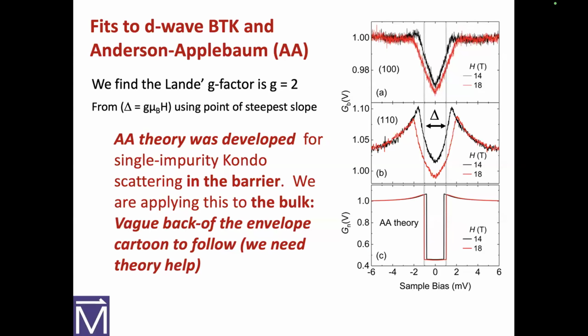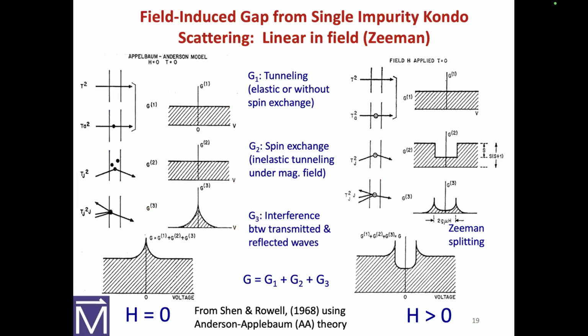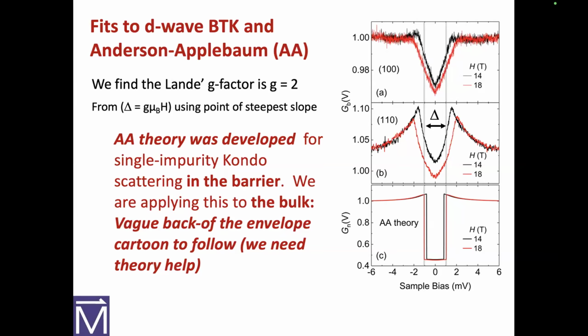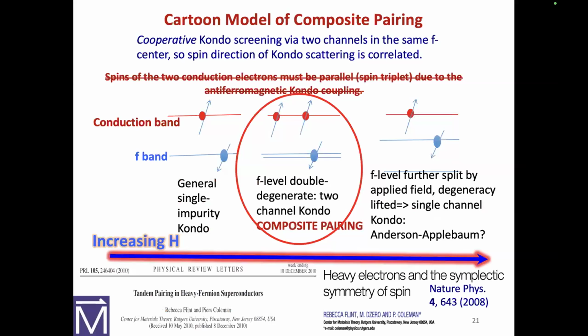And this is some statements on the Landé g factor. It's approximately 2. This is just showing that this theory here was the Anderson-Appelbaum theory, and I don't think it's any big deal to tell you that we can fit the data with BTK, and we can fit Anderson-Appelbaum, that's linear splitting. There's a lot of parameters in there. I'm not sure we can know.